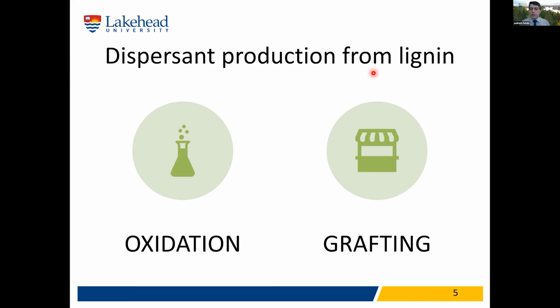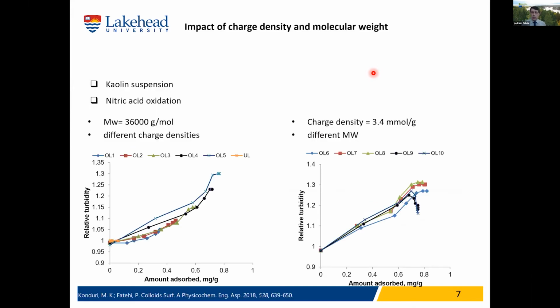But if you want to produce dispersant, there are different methods, but there are two main methods that I want to discuss today, and I want to compare them a little bit and see how we can produce them. So let's move to oxidation. When you look at the literature about dispersant production, people talk about the charge density and molecular weight of dispersant. So the first thing we did was to see how molecular weight and charge density of dispersant can affect its performance. To make dispersant, or charged low molecular weight lignin, we tried nitric acid because it's easy and it can decompose lignin easily, and our suspension model was kaolin clay because it's available everywhere.